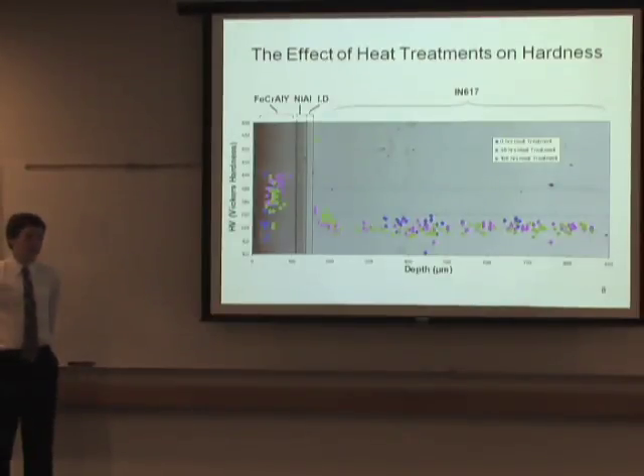And we have two hypotheses for this phenomenon. One, in that microindentation is perhaps too large for the FeCrAlY layer, and some of our indents were getting too close to the epoxy resin layer over here, or the NIAL layer right here, therefore giving us inaccurate hardness ratings. And two, brings us back to that process of interdiffusion.